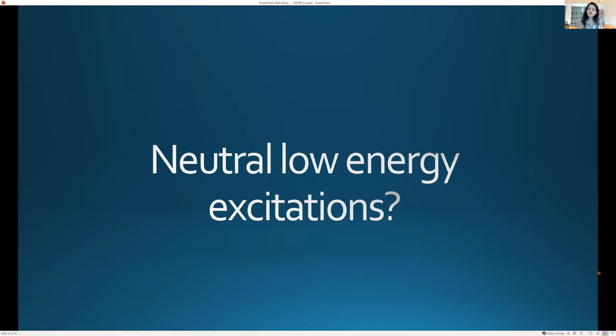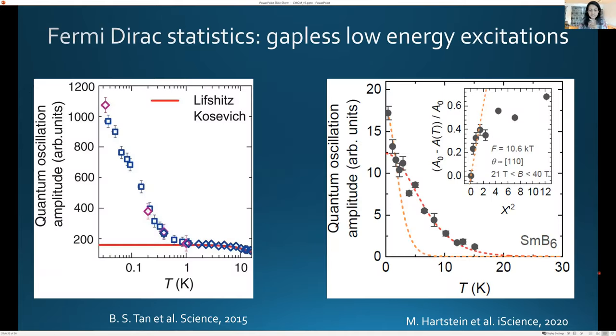So that's one possibility. However, before we get to that, we think of the possibility of, can one just have a gap and no low energy excitations, but still have the electron jumping across the gap? I'll show you the equation a little later on, but just for now, the main point I'm going to make is that for such a case where there's a gap and electrons jump across this gap, one would expect the quantum oscillation amplitude to plateau at low temperature. So roughly the size of the gap, below the size of the gap, you don't expect quantum oscillations to keep growing in amplitude. You expect them to flatten or decrease.